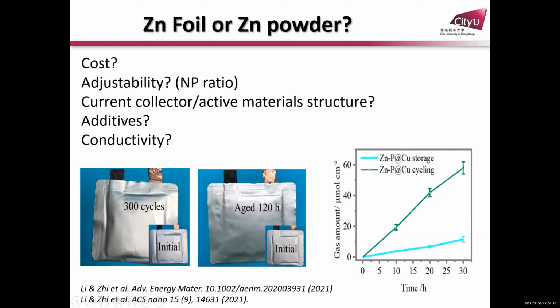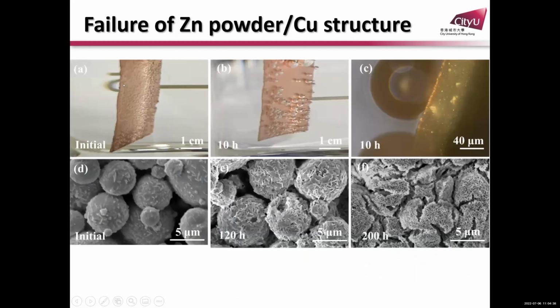So we tried powder. But powder has a large surface area, so you have a big issue of hydrogen evolution. You see that, zinc P is zinc powder. If you use copper as a current collector, even without cycling, only for storage, you get gas evolution. And even if you put this zinc powder coating on the copper current collector, you see the gas evolution is very severe, and the zinc particles get broken in a short time.